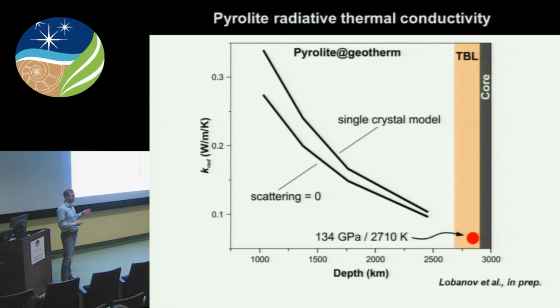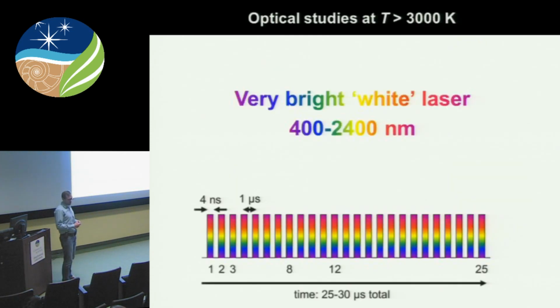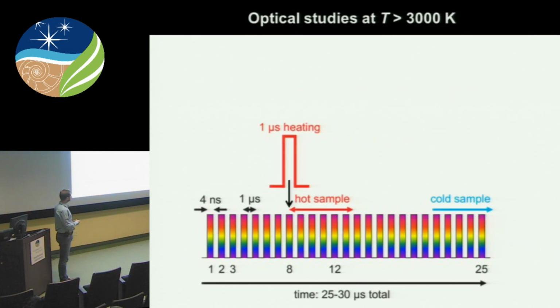But the important thing is that near the core-mantle boundary, and this is the region where we want to know the radiative conductivity the most, its value is likely negligibly small. So one of the takeaway messages is that in geodynamic simulations, you can basically neglect radiative transport altogether.